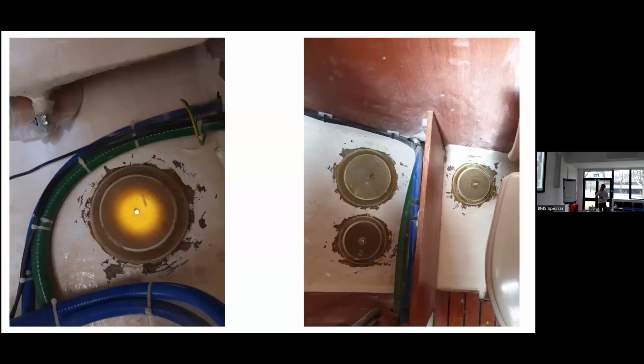And on the next slide, you can see that I fitted them. I fitted all of these with G-Flex, which was brilliant for bonding onto older GRP. You can see also I peel plied them. Anybody know what peel ply is? It's a fabric that you can rip away, which gets the surface ready to bond. That gave me the thickness that I wanted with what I felt was a good spread of load for a skin fitting.